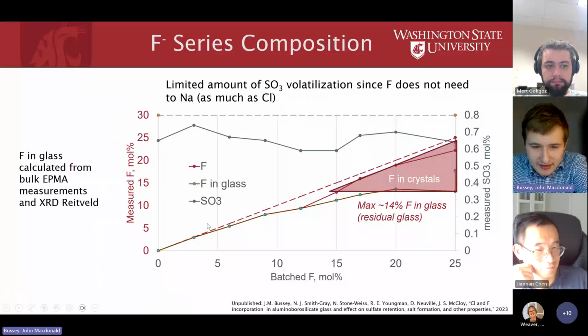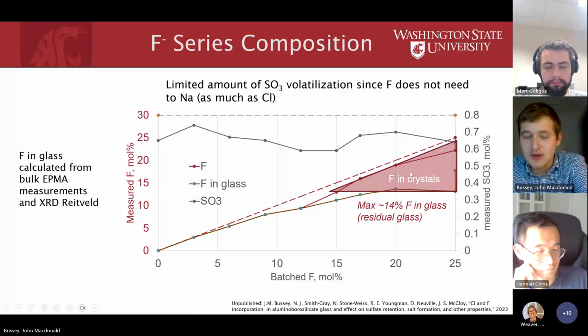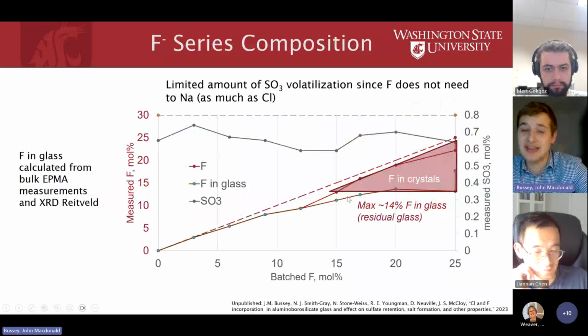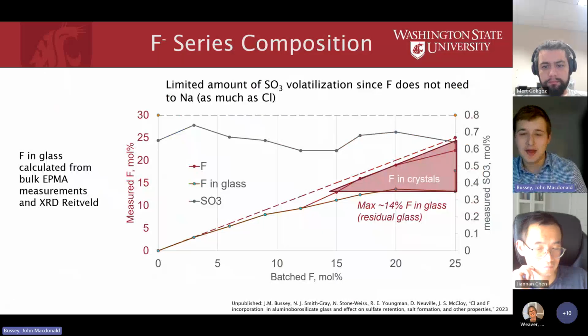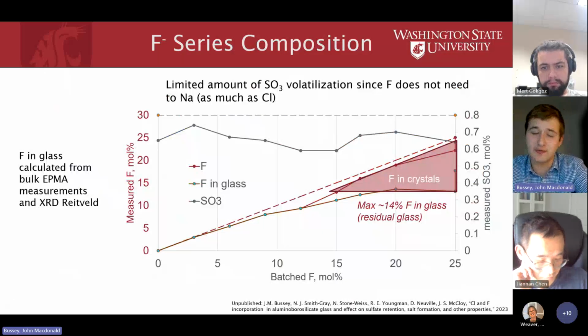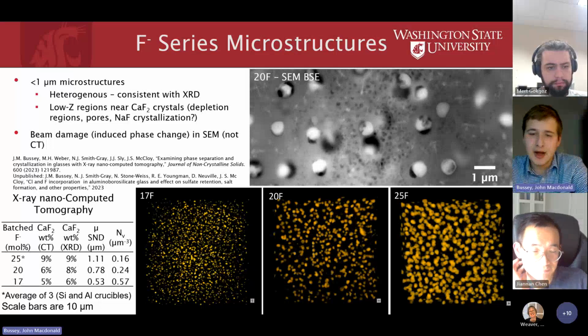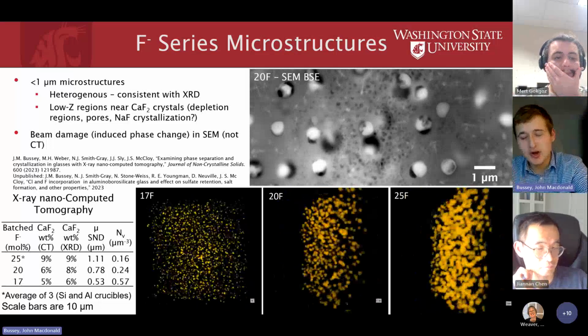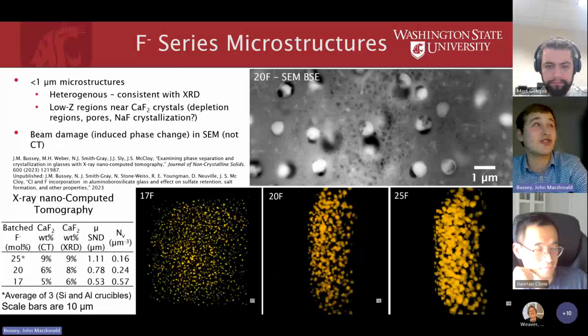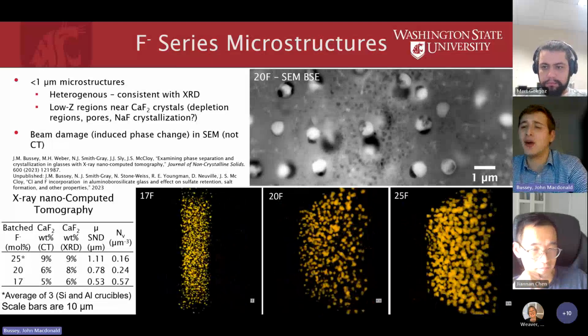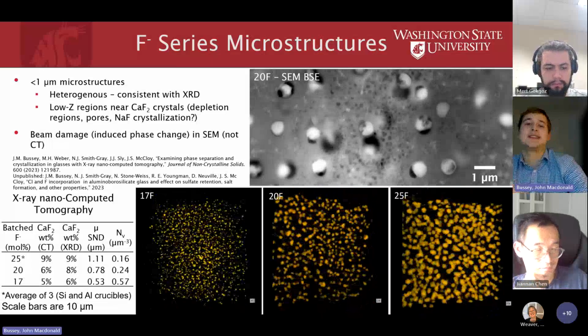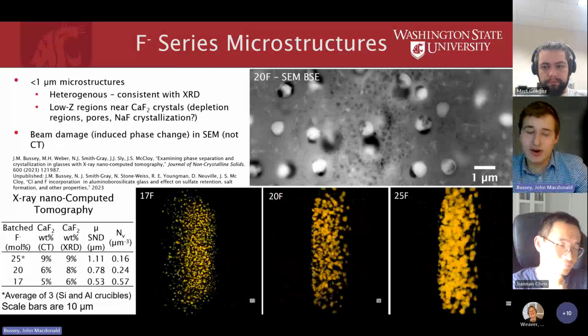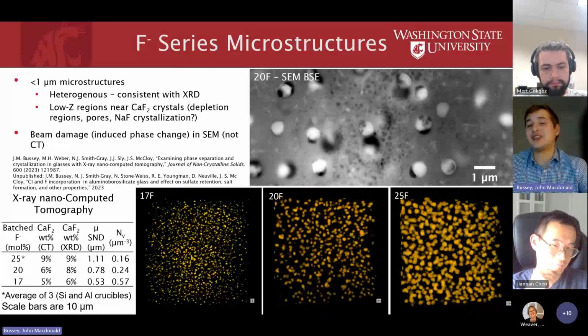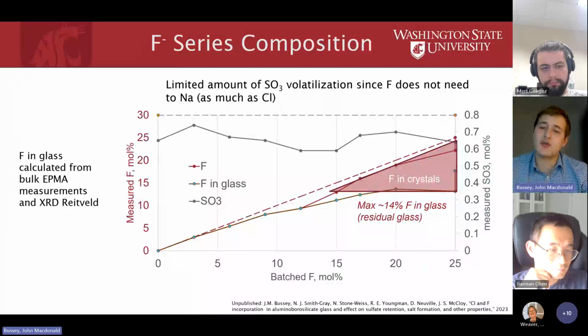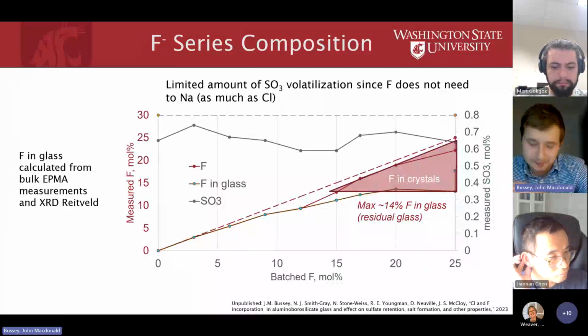Taking a look at the compositions, here in these blue circles we see the fluorine, and we see that the fluorine is almost entirely retained within the glass system. But we know that at about 15 weight percent we start forming these crystals, as you see here. However, the way we measured composition was with electron microprobe, and the smallest spot size we get down to is around 10 microns. You see in these images that 10 microns involves a lot more than glass; you get glass and all the crystals. So we know that almost all of the fluorine is retained within the system.